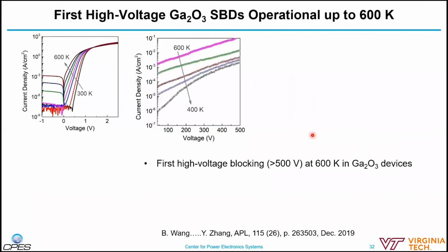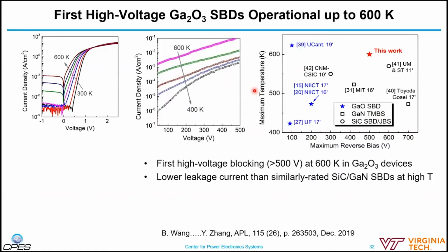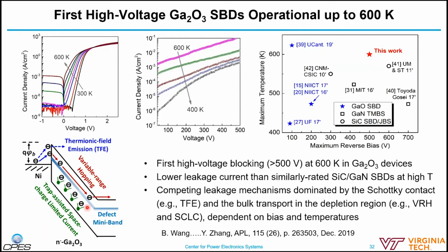And then we demonstrated better performance compared to the state of the art at that time. And then we tested these devices at high temperature, all the way up to 600 Kelvin, about 350 degrees C. We tested them to 500 volts, and we see that all these diodes are very robust. They can block very high voltage at high temperature. And then we compare the maximum temperature these devices can sustain under reverse bias. We demonstrated that these devices have lower leakage current than similarly rated silicon carbide and GaN Schottky barrier diodes at high temperature. And also, of course, we studied some of the leakage current mechanisms, which is also very interesting.